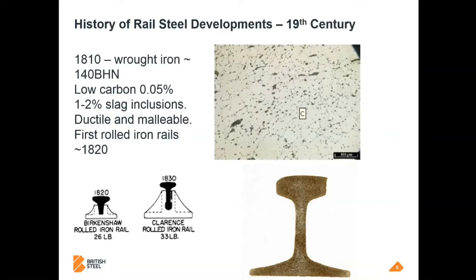and you've got a loss of your profile shape and some mushrooming, and it's been overwhelmed by the demands that have been put on it. So subsequent passes of trains, each train is exerting an axle load. In the UK mainline traffic, it's about 22 tons per axle, and it's a 5 pence piece sized contact patch, so you can imagine the pressures are enormous. As subsequent axles pass over the rails, they start to cold roll it effectively and mushroom it out. So increased strength resists this loss of profile that results from the plastic deformation. So we've got to drive the strength up.